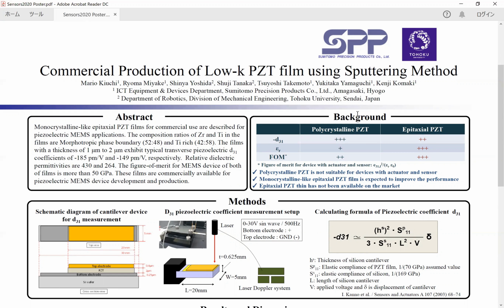However, so far, the epitaxial PZT thin film with both high D31 and low permittivity has not been available on the market because of the trade-off between them. So we have developed commercially available epitaxial PZT thin film on silicon wafers. The PZT film has two kinds of composition ratio of zirconium and titanium. They are MPB and titanium-rich. By taking into account this, the impact on D31 and permittivity are demonstrated.